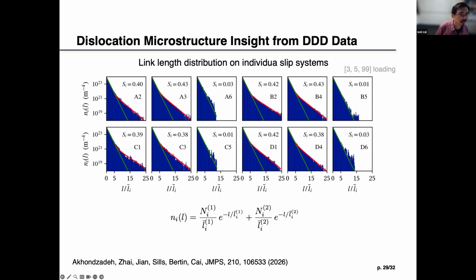The statistics here are very rare, but if we average over many configurations, we get those data. And we found that at this large length, there's a long tail that follows a different distribution. We characterize it using 2 exponentials. So how does this relate to what we want to do?